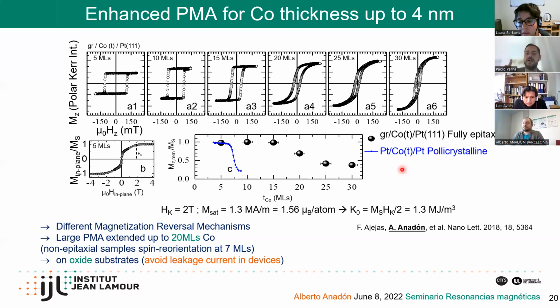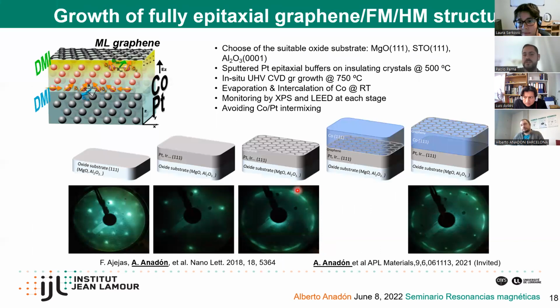But anyway, the LEED pattern already indicates that you have graphene. For example, in the third image here, you can see the typical feature of graphene on platinum. Due to the low interaction between the graphene and platinum, you have these rotational domains. Then when you grow cobalt on top, you lose the graphene LEED, and then when you intercalate, you get exactly the same picture that you had before. And in the case of iridium and ruthenium, you can even see the Moiré pattern. So this is already a proof. You don't need to do Raman also, but it's good.